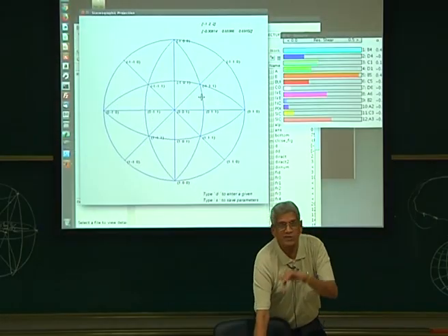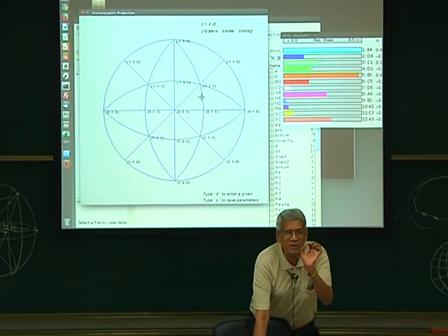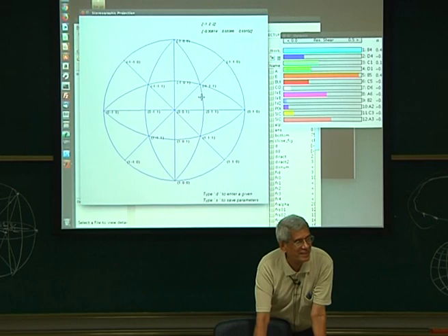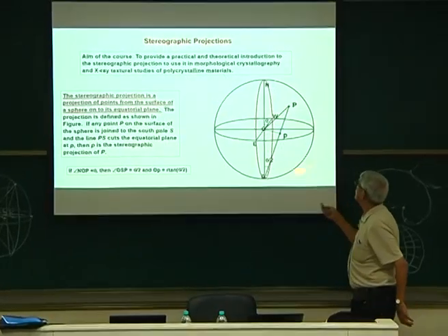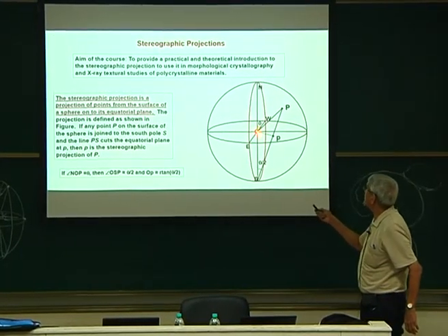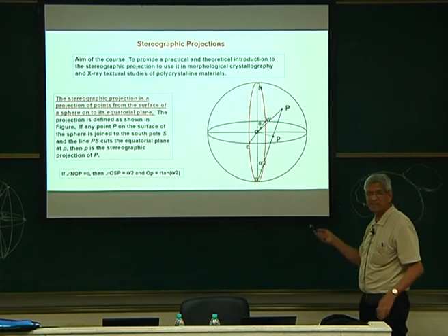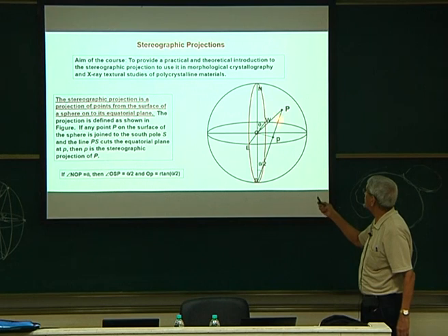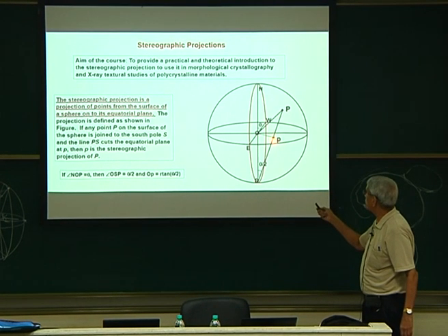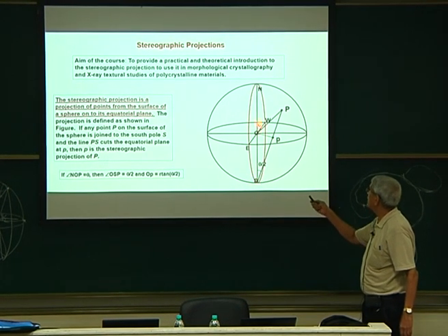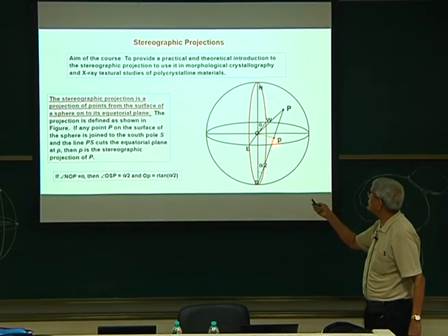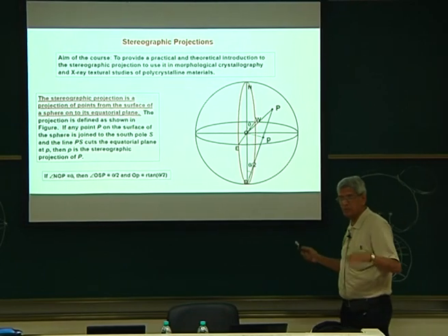In fact, there are lots of slides, but I will explain some essential features of stereographic projection. You can see that any line which we draw from the center is radial. It's like an outward normal which comes and meets at this particular point, and it makes a projection when we view it from here. As I mentioned, from geometry we can find this angle, and this distance will be r tan theta by 2, correct?